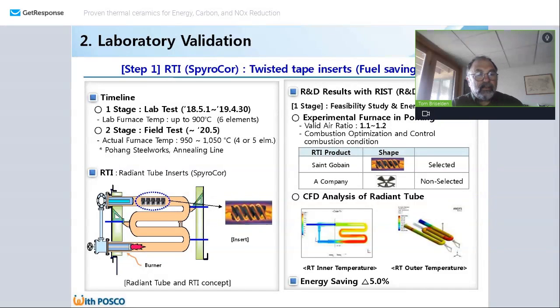In the laboratory trial, they saw a 5% fuel savings. And this was at temperatures between 900 and 950 degrees Celsius. The system that was used was 6 elements. However, the field test was actually performed at 950 to 1050 degrees Celsius. But again, looking at the lab test, they optimized the combustion air ratio from between 1.1 to 1.2. And they also did examine 2 types of inserts, the Saint-Gobain product, the SpyroCor, and then what we would consider a competitive technology. Just through the laboratory evaluation and the energy savings they saw, they selected the SpyroCor. They also did some computational modeling in the radiant tube, and through that also found similar energy savings of 5%.